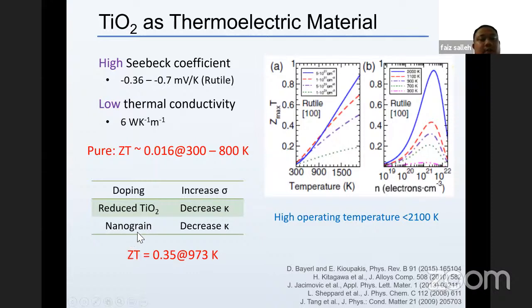And then we can reduce the TiO2, which is the oxygen vacancy inside the TiO2 lattice. So we can decrease the thermal conductivity and also introduce nanostructuring. It also can decrease the thermal conductivity by introducing phonon scattering and grain boundary scattering. And currently, the highest reported ZT is 0.35 at high temperature, around 973 Kelvin.